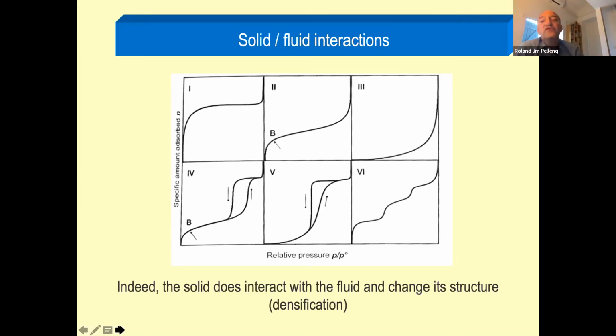Now we move to porous material. If you take a meso-porous material, as I said, a pore size where we do maintain phase transition, that's typically what's happening in plot number 4 for a solid porous, mesoporous material, where we have capillary condensation, characterized by that hysteresis loop.